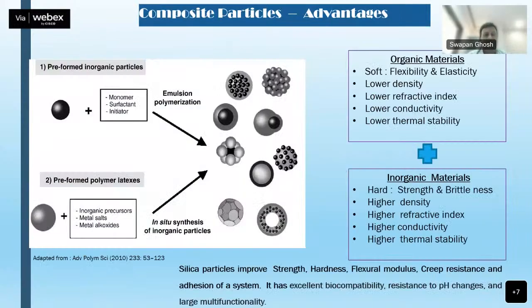Coming back to the composite particles, you can see that composite particles are nothing but a marriage between organic and inorganic materials. From the organic side, we can think about properties like, for example, polymeric materials are very soft. So you can think about flexibility and elasticity, which are critical properties that can come from organic materials. Then others: they are of low density, refractive index, conductivity is low, and usually they are of poor thermal stability.